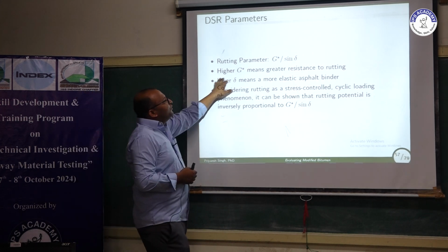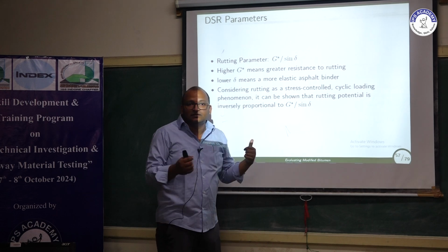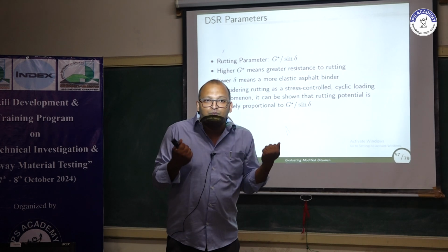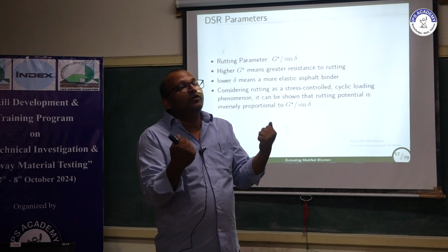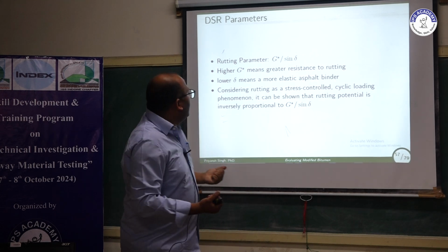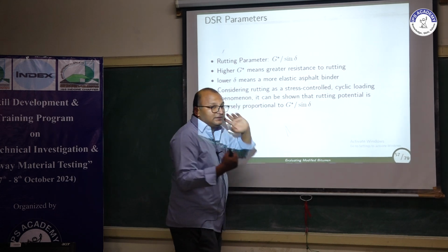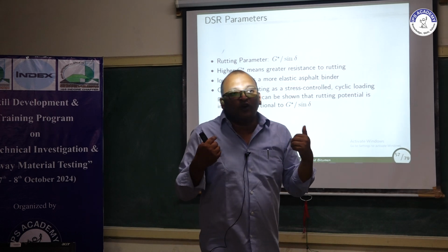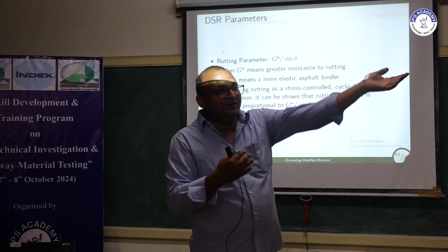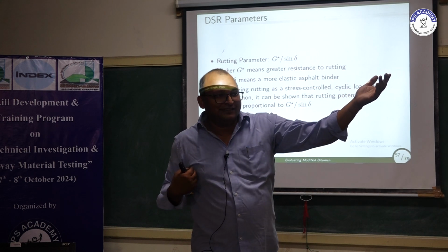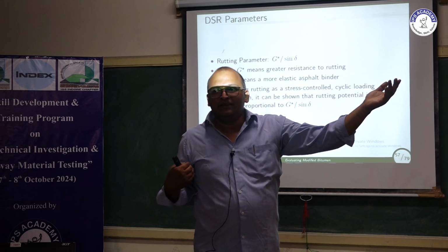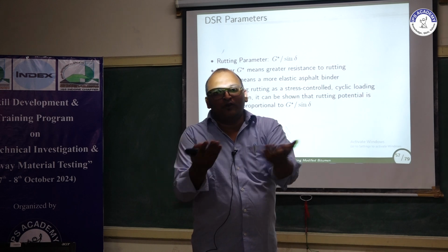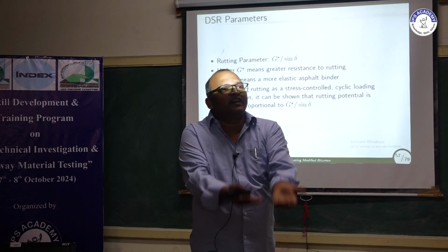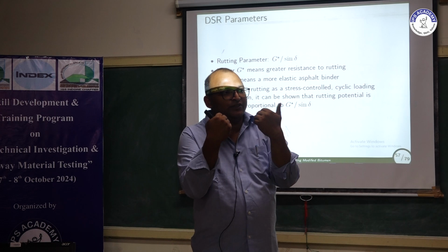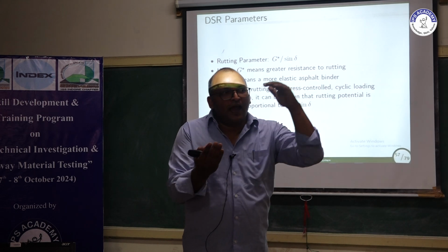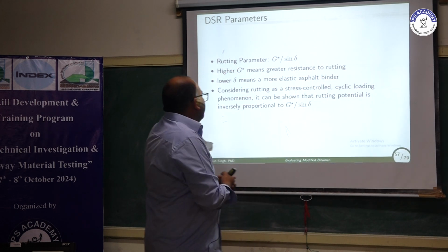Now what it signifies: if your G star is higher, that means your material is stiffer. More stiffer means it will undergo less rutting or less deformation. And if your delta is low, that means your material is more elastic. So what do you want? You want better stiffness and more elasticity, isn't it? From a binder, you want whatever deformation is there to recover quickly, isn't it? So we want more elasticity and high stiffness at the same time.